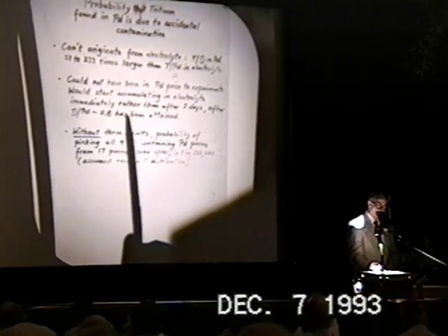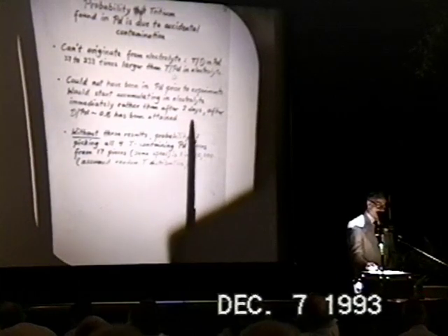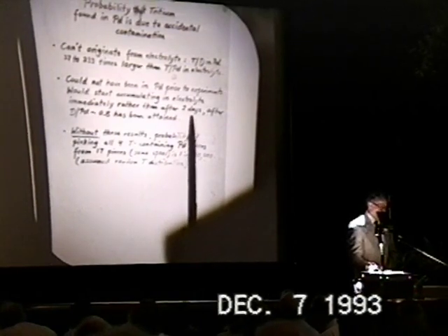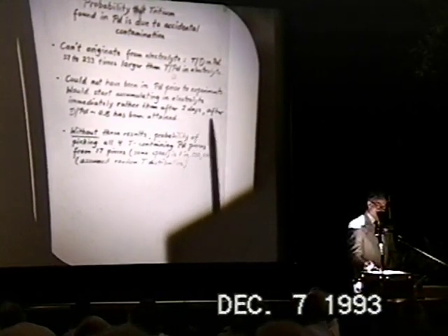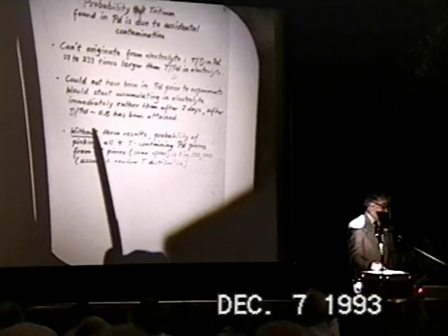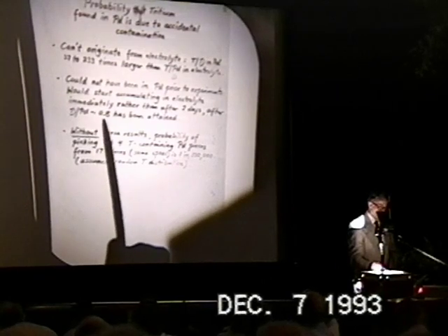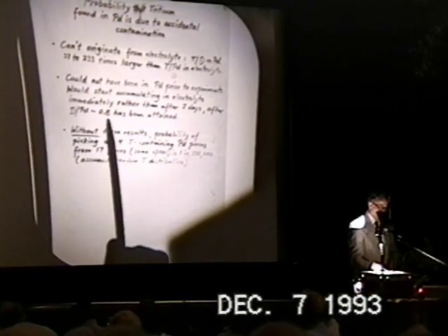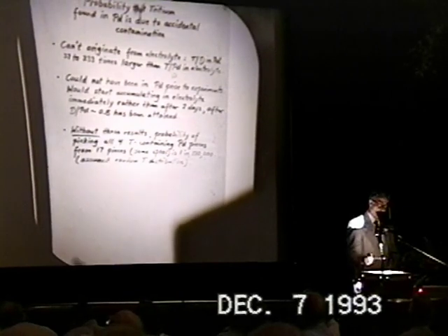In truth, what we find is that it takes about 2 days to find any tritium in the electrolyte, and that coincides with the 2 days we typically need in order to generate a loading ratio of 0.8.